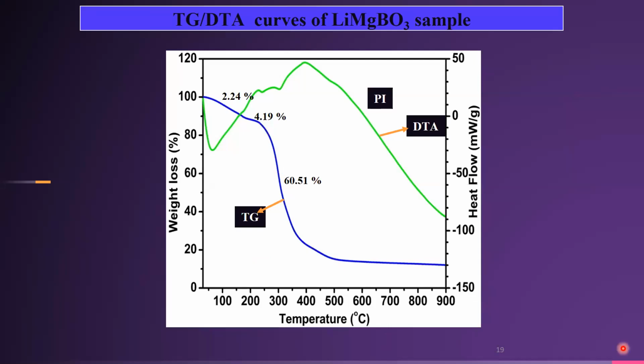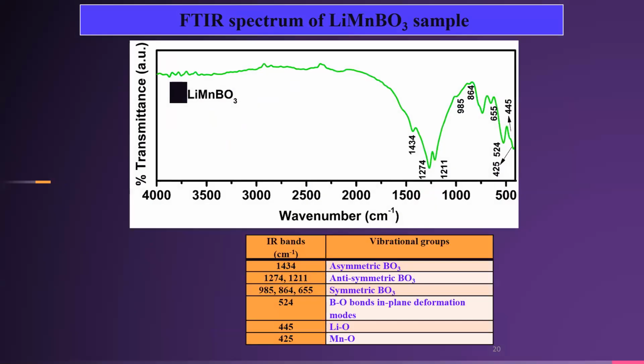Observed above 500 degrees centigrade, which confirms that no further decomposition occurs in the sample after 500 degrees centigrade, which confirms that the lithium magnesium boroxide sample is formed above 500 degrees centigrade. These are the different FTIR vibrational modes of the lithium manganese boroxide sample, which we compared with the reported literature values, which confirms the formation of the lithium manganese boroxide sample.